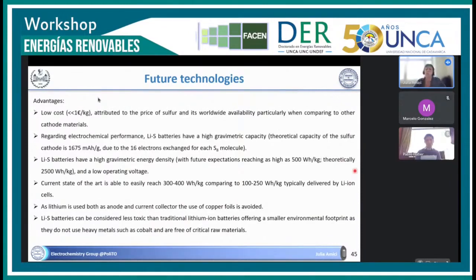For now, the next expectation is 500 watt-hour per kilogram for the lithium sulfur system, but theoretically it should reach 2,500 watt-hour per kilogram at low operating voltage. It also uses lithium metal as an anode, and usually a liquid electrolyte, but some solid electrolytes are also under study. Another interesting fact is that it's very low cost, because sulfur is very cheap. And it does not use any critical raw material like cobalt, because you don't need so much of this kind of material.